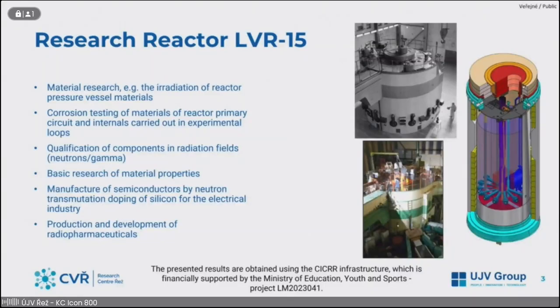I'm not going through the utilization, as this was already mentioned in Marek's presentation, but for the material research experiments, there are two key features. One is the received neutron fluence and radiation damage which the material receives. The other important parameter is the irradiation temperature to which the material is exposed during the irradiation. In most irradiation experiments, we aim to have this temperature as close as possible to the temperature in the environment of the nuclear facility for which we aim to use the material that we irradiate.